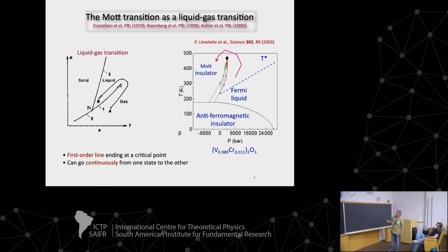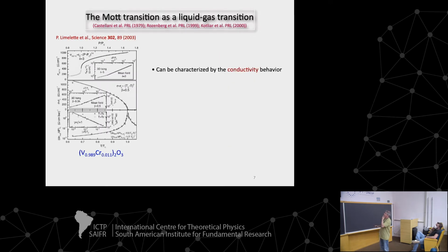Okay, so here I want to just bring the similarity between the Mott transition and the liquid gas transition to you. So this is the conductivity data for the V2O3. So for instance, this is the conductivity. I don't have data here for the conductivity below the critical point, but below the critical point, you have a very large drop in conductivity as you go from the metal to the insulator, sometimes 4 orders of magnitude drop, so it's a clear phase transition.